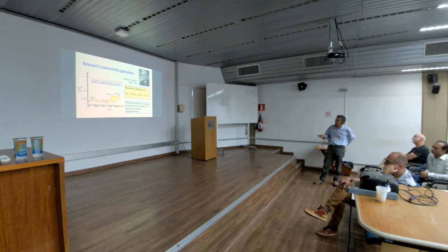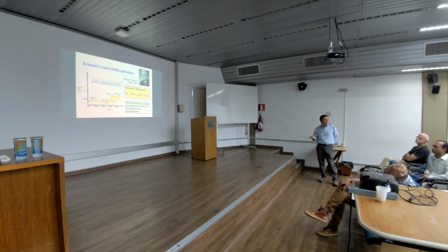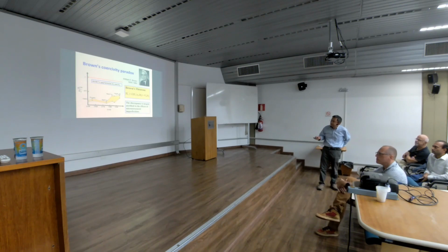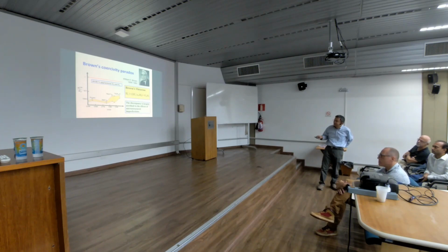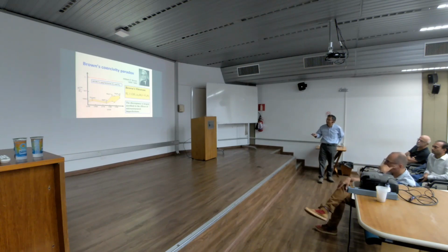Okay, and this is magnetization. So if this HA is 1 here, then what he predicted is your coercivity should be above this red line. However, practically, what we can make, this ratio of coercivity over HA, is far below half, 0.5. Even when we tried very hard, there is some progress, but it is still much lower than the lower limit he predicted. So we call this a paradox.